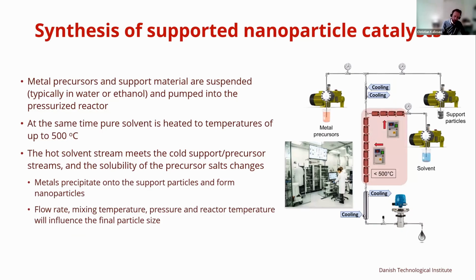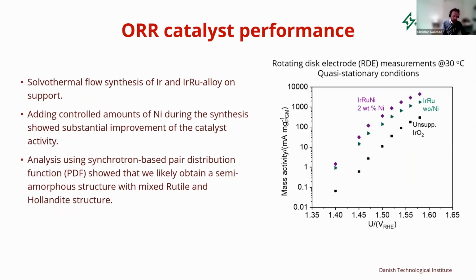We can do this flow synthesis, where we can have support particles in one pump, we can have precursors in the other, and we then heat it up and develop these particles in a very short time span. Temperature, pressure we can control, and therefore we can also control the outcome of the particles to a very fine degree. And what we then developed was iridium with ruthenium alloys on support,